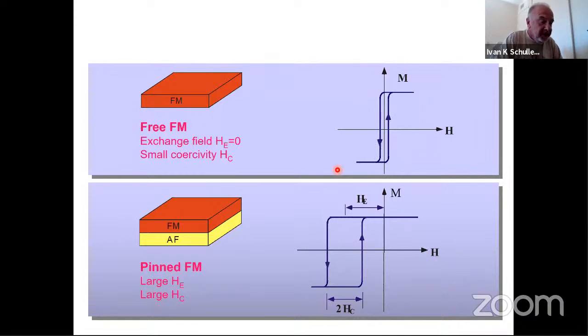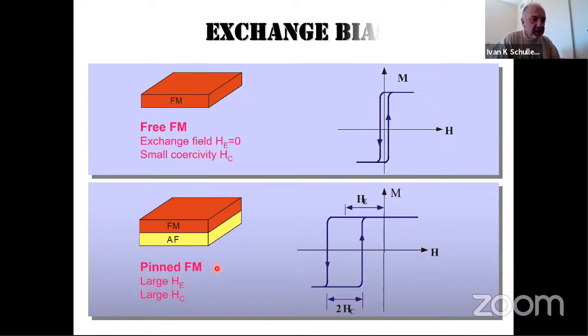Now, the explanation of this is very simple. In a ferromagnet, you have this so-called hysteresis loop, and the magnetization versus field has this form here. Now, if you put this ferromagnet next to an antiferromagnet, because of the interaction at this interface, the hysteresis loop shifts to negative values. It's like an internal field, it increases the coercive field, and it shifts by a large amount called the exchange bias field. This is what is called the phenomenon of exchange bias.